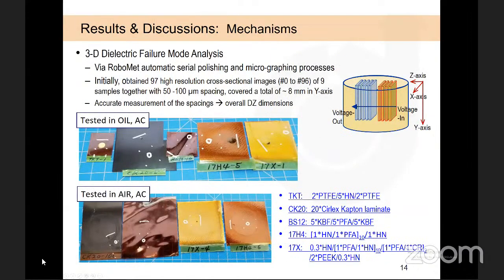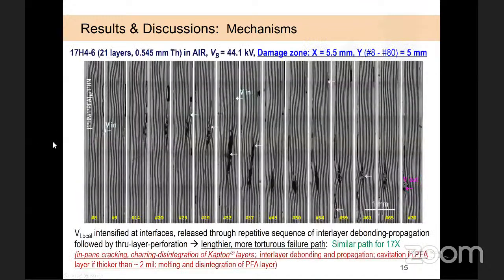The analysis was done relatively easier with the RoboMet, the automatic serial polishing and micrographing system. Initially, we started with 9 representative samples as shown in the pictures. They were mounted into one RoboMet sample to save time and efforts. All samples were aligned by the coordinate system, and the distance between each cross-section was monitored accurately for the overall dimensions. This slide shows a sequence of representative cross-sections from the 17H4 sample failed in air.